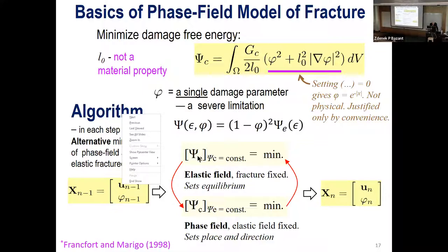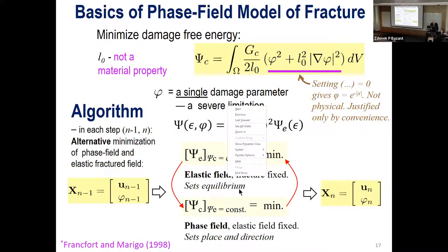So first we minimize the elastic free energy, keeping the free energy of damage constant, taken from the previous step, of course. And then we take this elastic free energy as constant and minimize the damage. And this can be iterated. But it does not need to be, and it converges actually very well. That's a very effective algorithm.